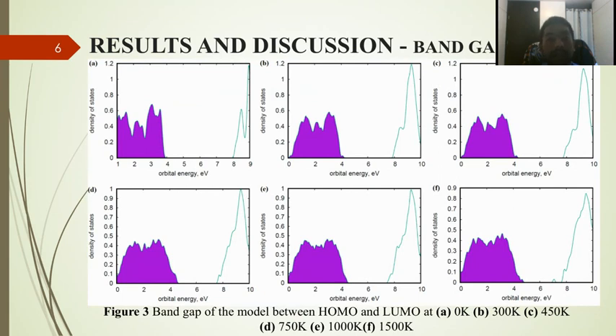So you see the band gap. As you see, the total energy is decreasing. The band gap is decreasing with the increase in the temperature. So this is the graphical view. So if we go to the next slide, you will see the tabular form.